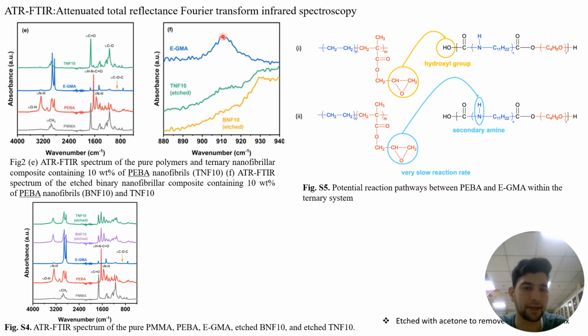Here a clear 911 peak is observed, which is related to the epoxide ring, while here it is not present. So it means possibly the epoxide ring of EGMA starts to react with the hydroxyl group of PEBA and the epoxy group starts to react with the secondary amine. This reaction is very fast and this one is very slow. It is a secondary amine, this is very slow.